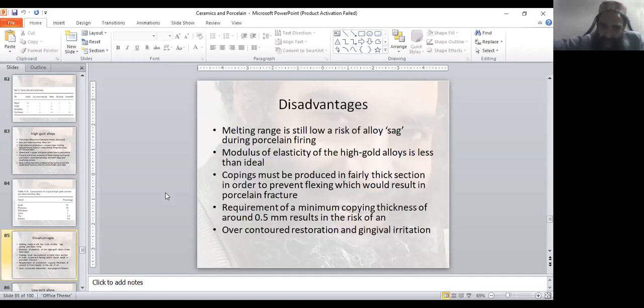Disadvantages: melting range is still low, a risk of alloy sag during porcelain firing. Modulus of elasticity of higher gold alloy is less than ideal. Copings must be produced in fairly thick section in order to prevent flexing, which would result in porcelain fracture. Requirement of a minimum coping thickness of around 0.5 millimeter results in the risk of an over-contoured restoration and gingival irritation. And what is this sag? Sag means deformation under its own weight.